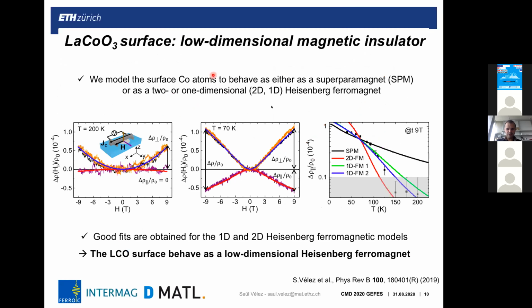So what we did was to use the theory that I explained before and model the surface as responding as a superparamagnetic system, as well as a low-dimensional ferromagnetic system. We could get nice fits of the magnetotransport in the system, from the fits of the superparamagnetic system and different models of two-dimensional and one-dimensional material. We can qualitatively explain the temperature dependence of this magnetotransport in the system as related to the surface behaving as a low-dimensional ferromagnet.